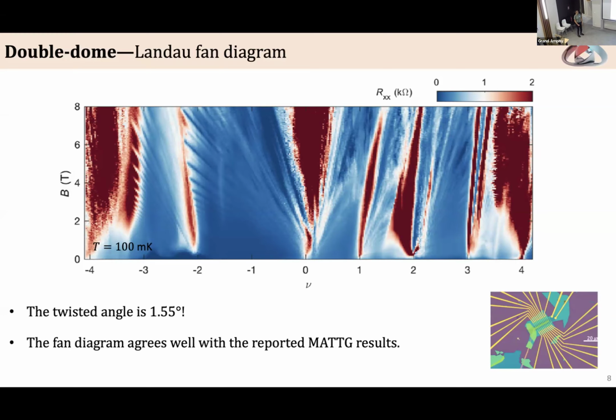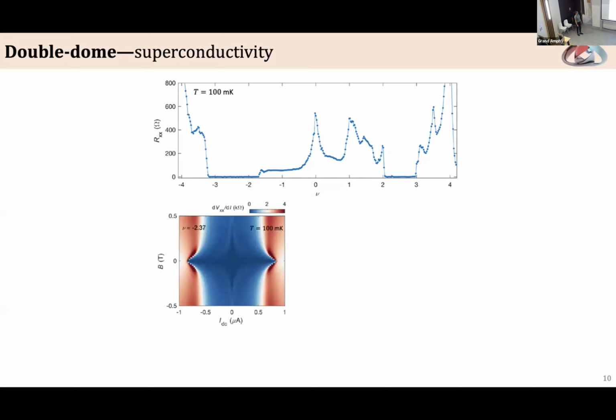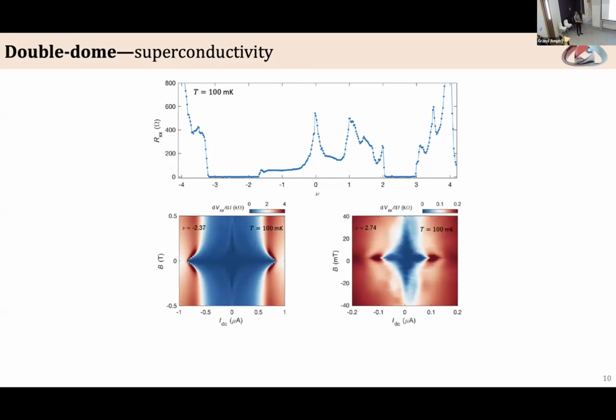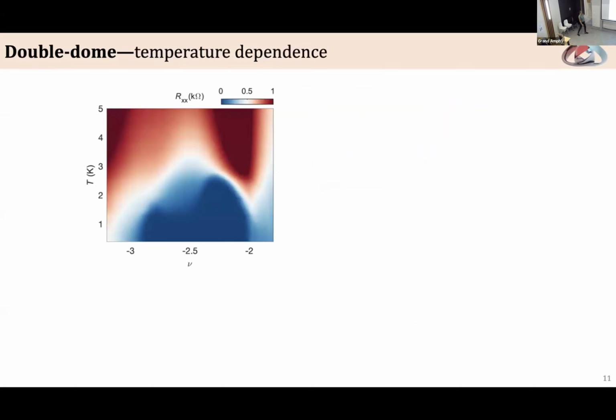So what did we add in the literature, if at all? What we found out is that this superconducting state that we have here, and also on the electron side in graphene, I must tell you is not always symmetric. The results in electron and hole are not symmetric when we talk about superconductivity. So what we found is a superconducting state in both cases, but the moment we started looking into the temperature dependence, and I know you may have to be a bit kind towards my data, there is a kind of double dome feature in the superconducting state. So this dome is not just a single dome, but there is some suppression of this Tc, and then it goes up again.